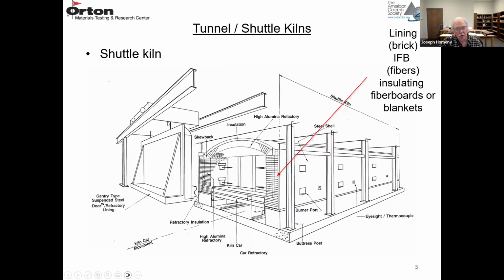And then a shuttle kiln is a batch operation. Again, no corrosion issues. There's no molten materials, no thermal shock issues. So they're, again, lined with IFBs, insulating firebricks, or some type of fiber insulation. So this type of furnace is loaded. There's a door that's closed. You go through the firing cycle, you open it up when it's cooled, and you unload the furnace.